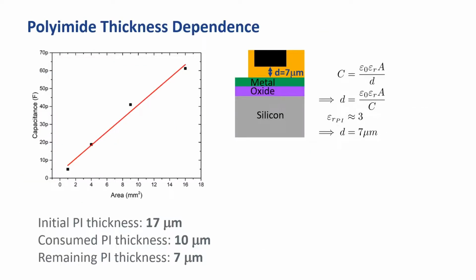The remaining polyimide thickness beneath the top surface of the leg was estimated by producing a series of square structures to act as parallel plate capacitors with the base metal structure. Knowing the dielectric constant of polyimide, the remaining polyimide thickness is approximately 7 micron, with 10 micron of polyimide having either been converted or ablated during the conversion process.